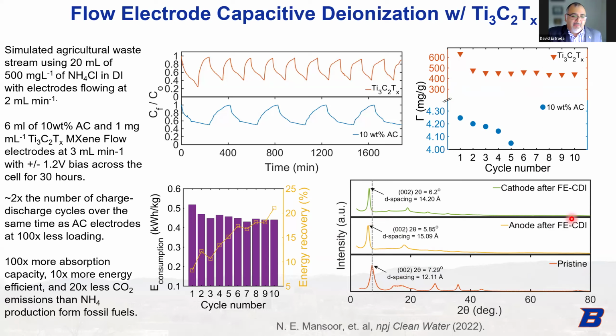And so we were able to remove the anolyte and catholyte at different parts, right? At the minimum here, and then do X-ray diffraction analysis and show the expansion of the d-spacing parameter, the 002 peak, right? And so that tells us that the ammonia ions are being captured between the layers, expanding that lattice, and it comes out to about 15 angstroms, which is about 4 ammonia ions if you were to stack them on top of each other. So that helps explain why we're able to get much larger ion absorption capacity.